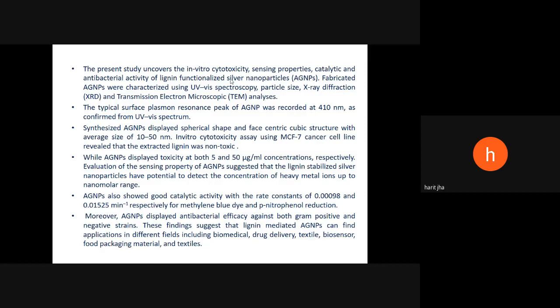It also showed a good catalytic activity with rate constant of 0.00098 and 0.01525 per minute, respectively, for methylene blue dye and paranitrophenol reduction. That is, it was also used for the catalysis of dyes. Okay, so the silver nanoparticle thus displayed antibacterial efficacy against both the gram-positive and negative strains. These findings suggest that lignin-mediated AgNPs can find application in different fields, including biomedical field, drug delivery, textile, biosensor, food packaging, etc.